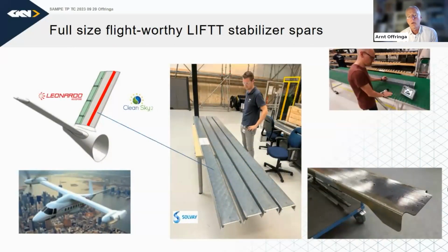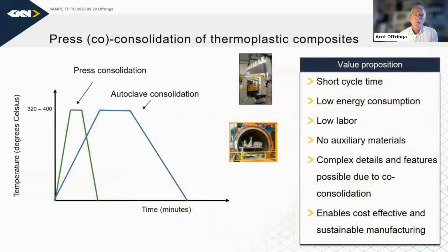So the flight-worthy spars are now ready, have been assembled into the tails of this tilt rotor aircraft, and will be flying, I think, by the end of this year, or was it early next year? And the reason to, once again, go out of autoclave is summarized in this graph, in the sense that we do have to go to very high temperature, between, let's say, 320 and 400 Celsius. But we can do this, the green line is the new process with a much shorter cycle time. And our calculations show that we should be able to save around 80% of process time and about 80% of the energy which we would otherwise need in the autoclave process.